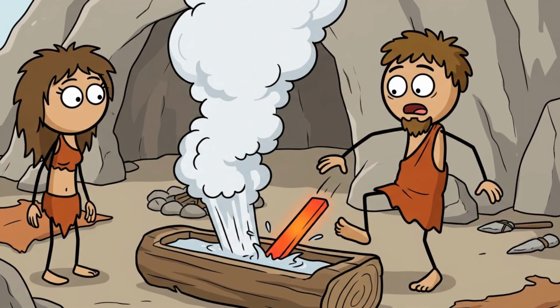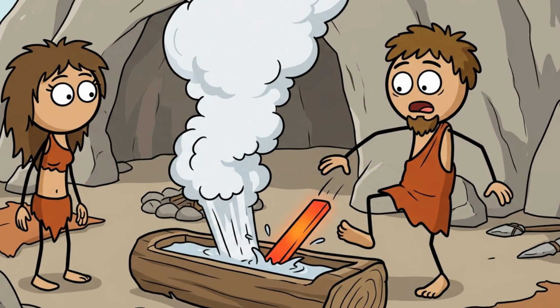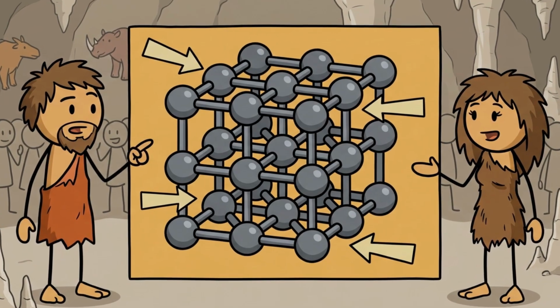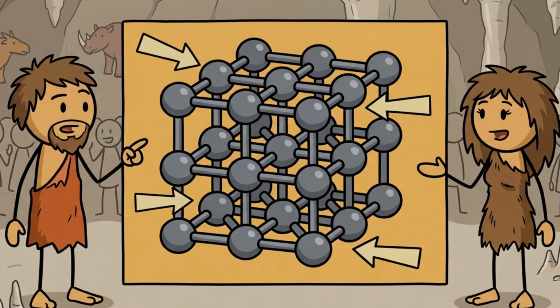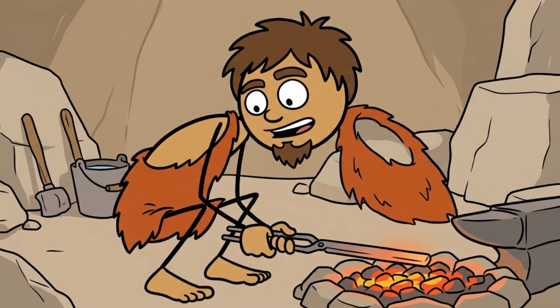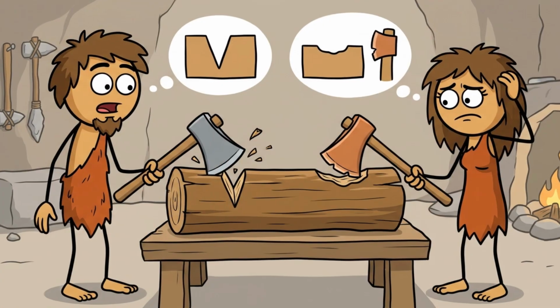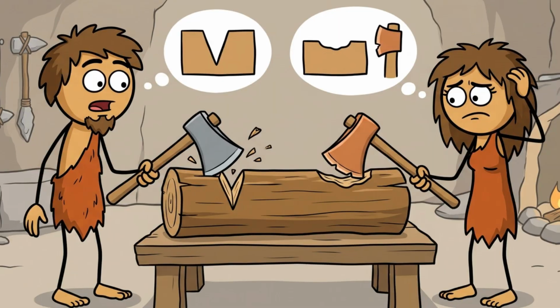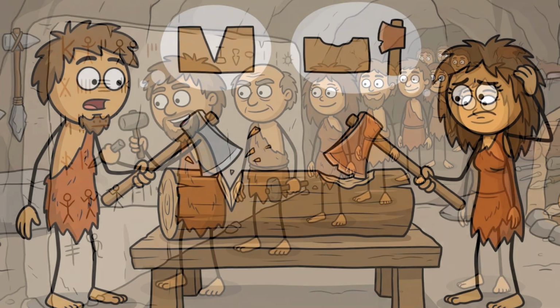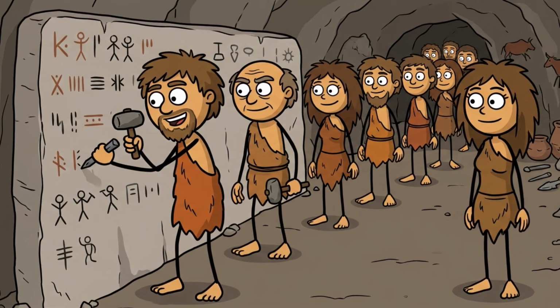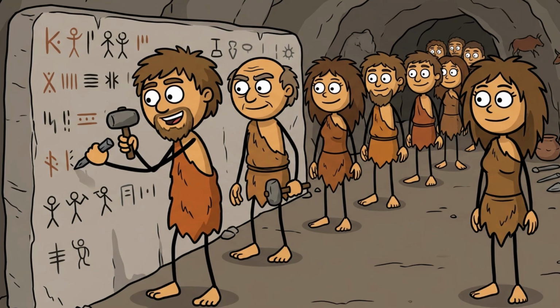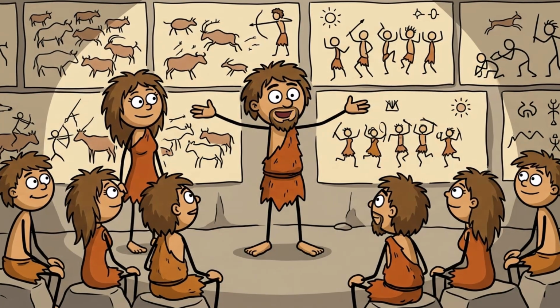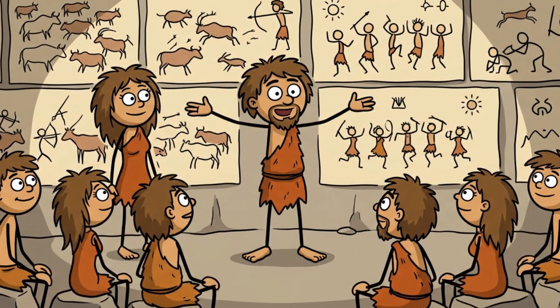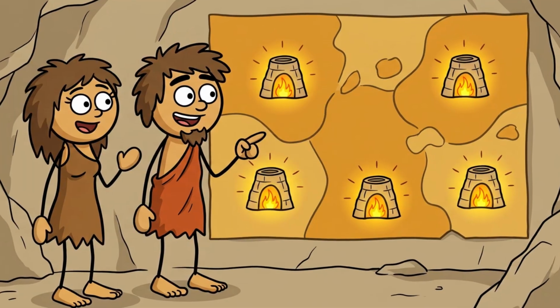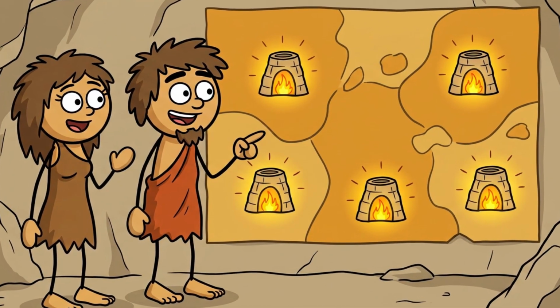Iron held in glowing charcoal absorbs carbon from the fuel at the surface, slowly, and the longer and hotter you work it, the deeper that layer runs. Smiths noticed that metal treated one way came out harder than metal treated another way, and started repeating whatever had worked. Then comes quenching. Heat carbon-bearing iron to glowing and drop it into water, and the internal structure locks into a hard, brittle form. Reheat it gently afterwards, and you trade some of that hardness back for toughness.